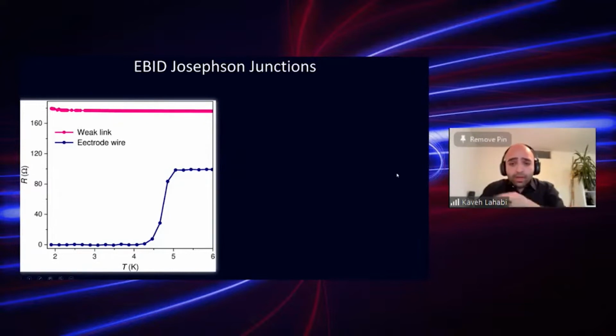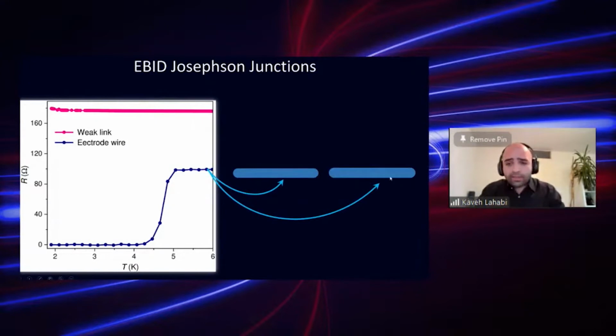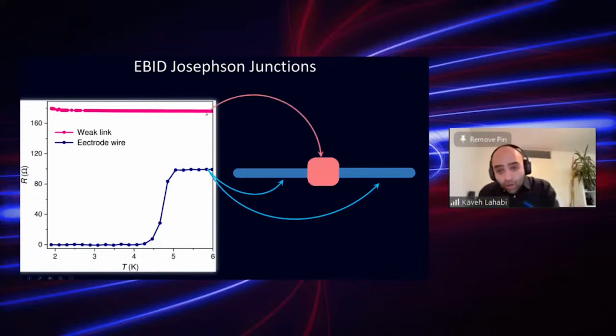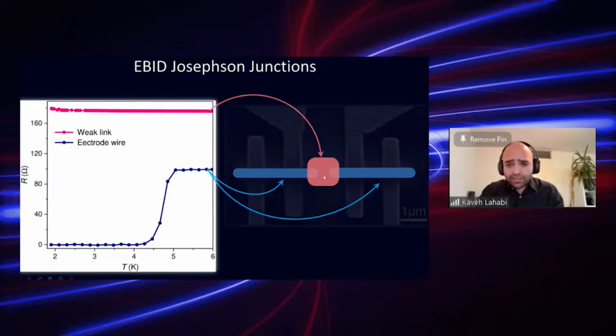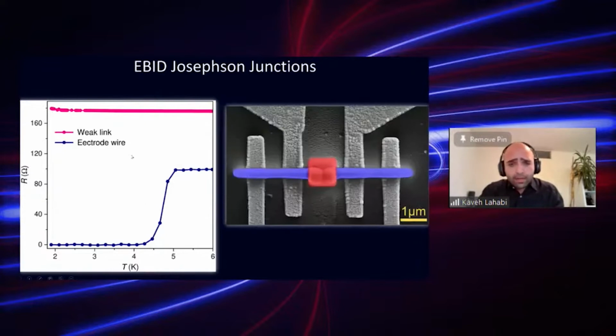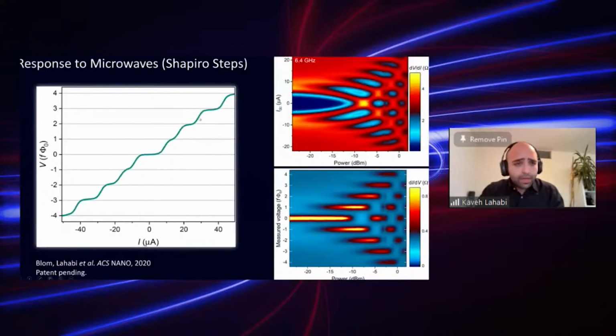First, we printed two superconducting wires with the slow scan, which were separated by roughly 160 nanometers. And then we connected them using this metallic but non-superconducting tungsten carbide to create the weak link. And this is an image of one of the earlier Josephson junctions that we made. And of course, later, here I'm showing you the Shapiro step. So this is the response to microwave radiation, and here is the response as a function of microwave power. But it's clear that we have Josephson transport.